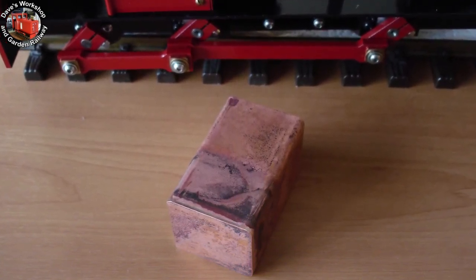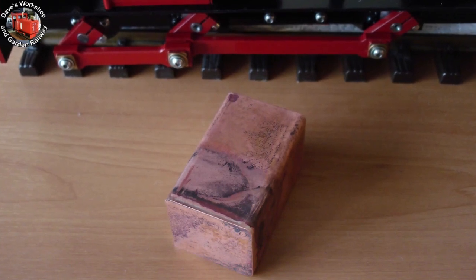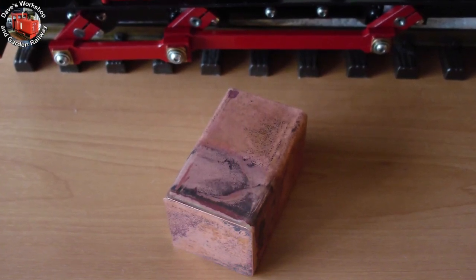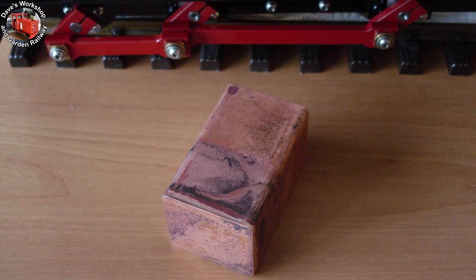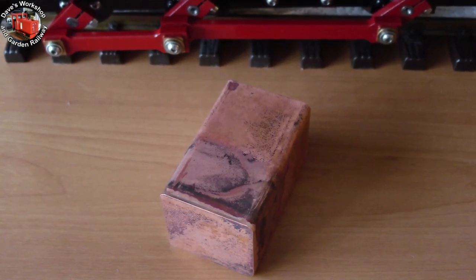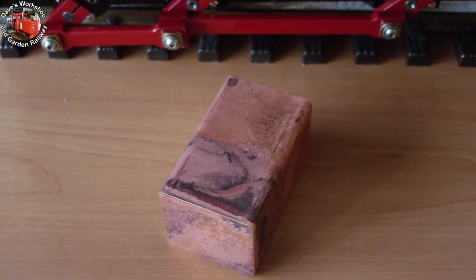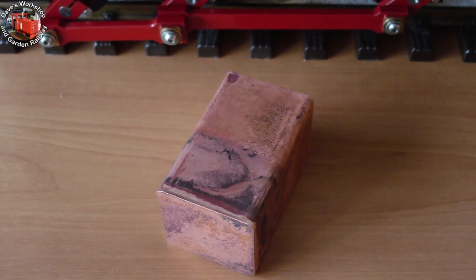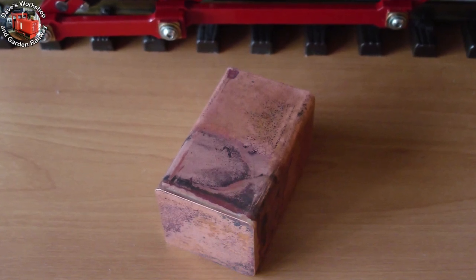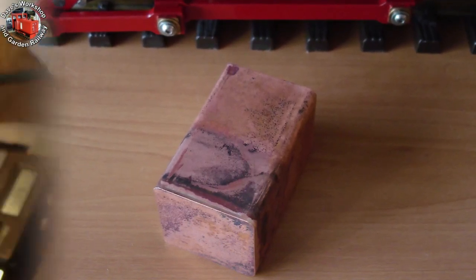The flux and braze were applied internally, snippets of silver braze, then heated vertically, placed on a refractory paper. 3 out of 4 pieces melted and flowed nicely. One didn't and cut my finger. I sealed it later with soft solder. That's a tank, not my finger.